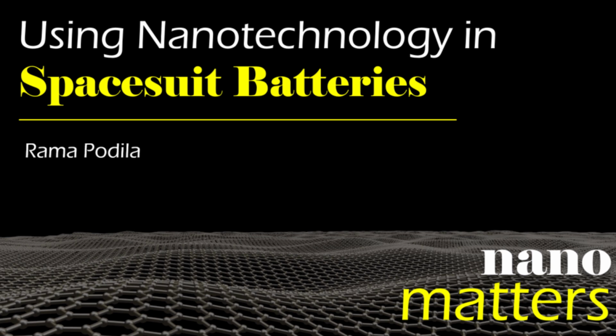And by increasing the surface area, we can definitely increase this charge, but it is still limited by the nature of carbon in this graphite. The other alternative is to use silicon. Silicon can store much, much higher charge compared to graphite, at least 2 to 3 times more.